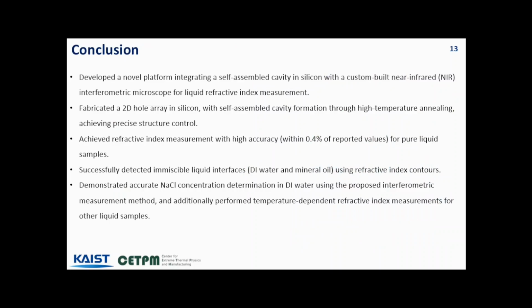To conclude, we have developed a platform that integrates a self-assembled cavity in silicon with a custom-built near-infrared interferometer for liquid refractive index measurement. We fabricated a 2D hole array in silicon where the self-assembled cavity formation was achieved through high-temperature annealing. And our platform demonstrates highly accurate refractive index measurement with values within 0.4% of reported values for pure liquid samples.